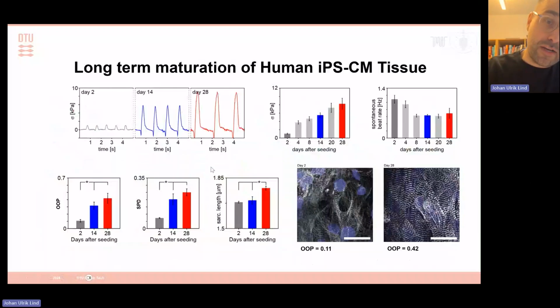And what can you use those devices for? You can study development in contractile force that we record from the resistance. As the tissue matures, we get an increase in contractile force as the stem cell derived tissue becomes more and more mature. You can see a decrease in spontaneous beat rate, which is also expected to decrease as the tissue matures. And this is reflected in microscopic changes. In this case, I plotted the sarcomeres. You can see that the sarcomeres become more and more oriented, and they also become longer and longer. Both are signs of a more mature tissue.